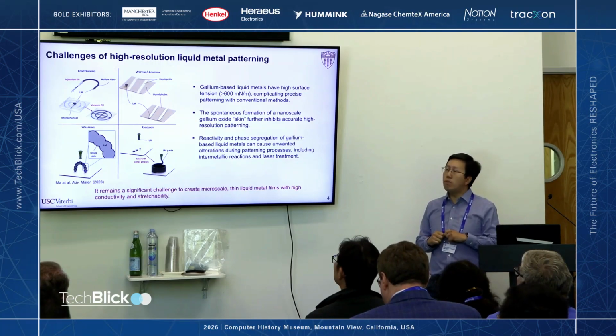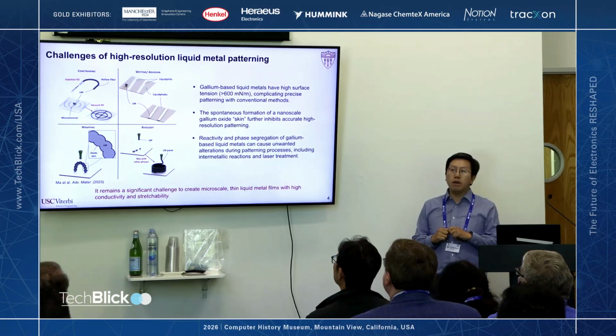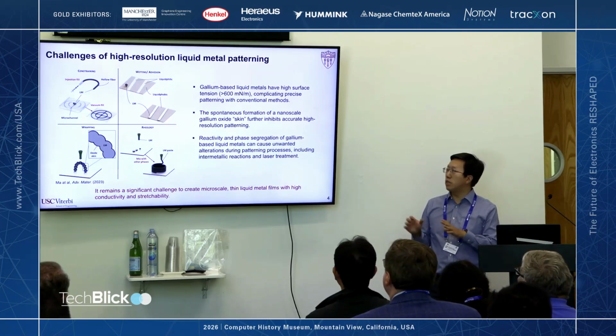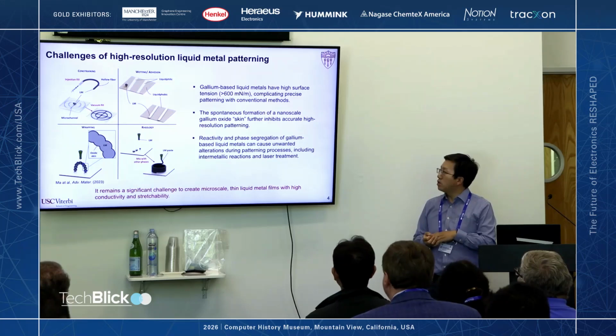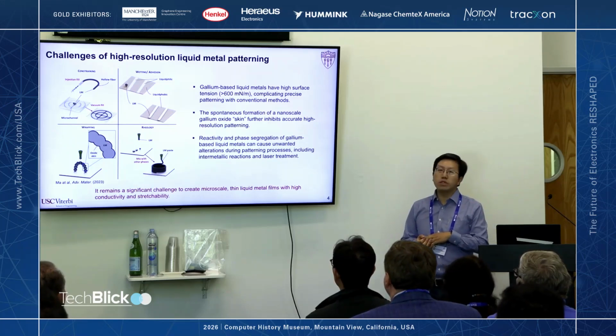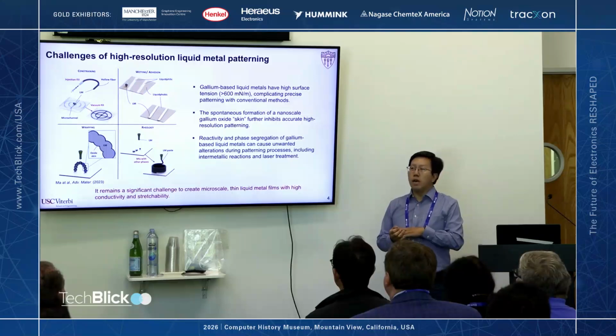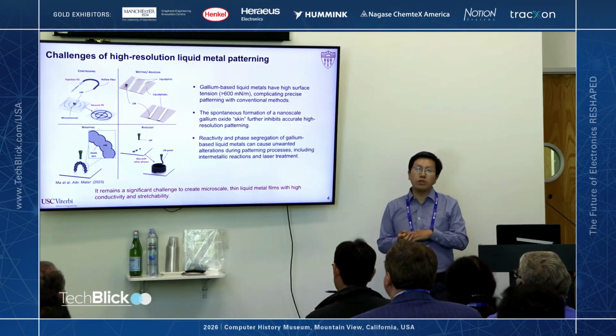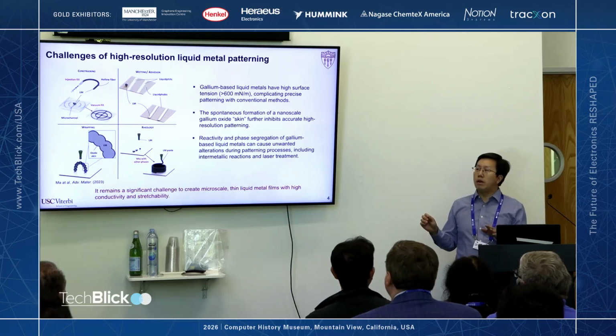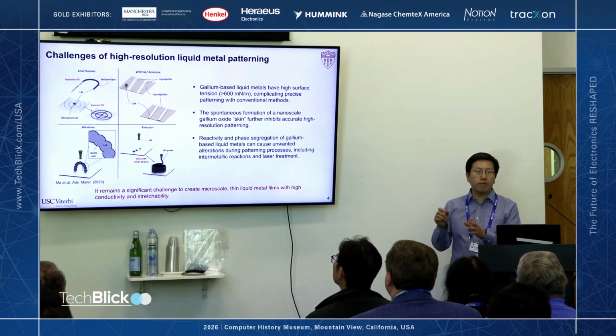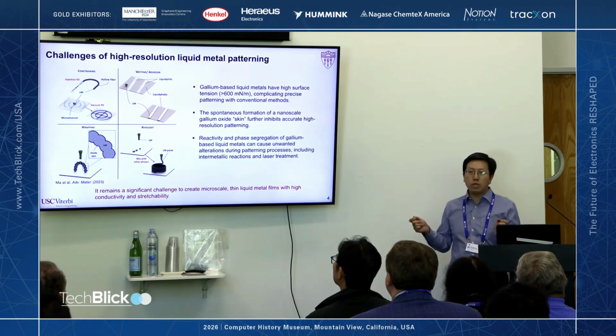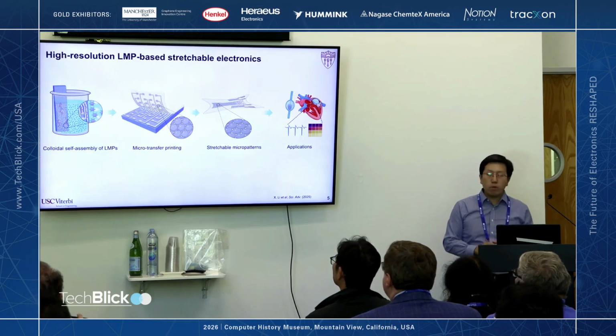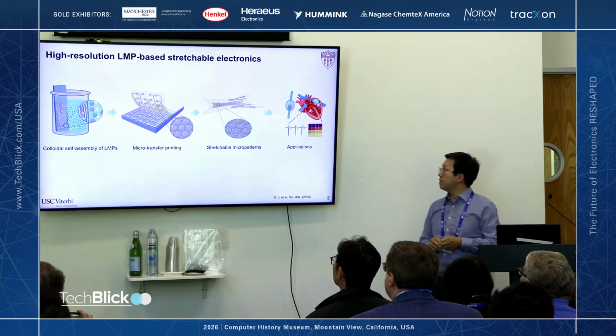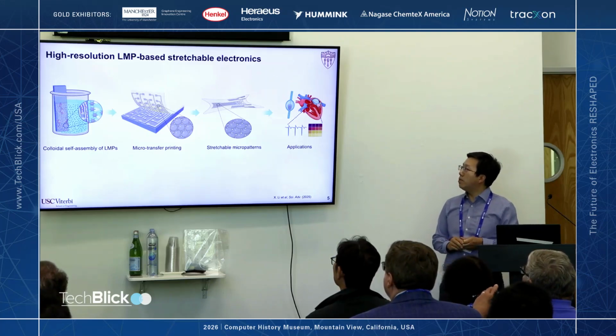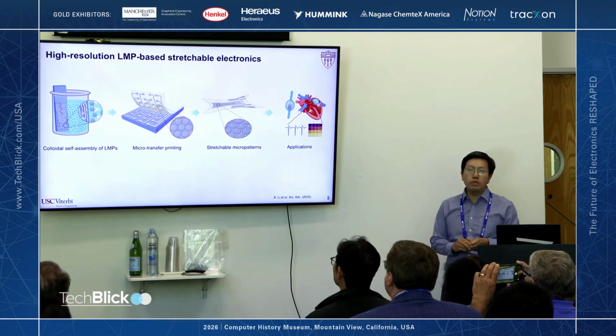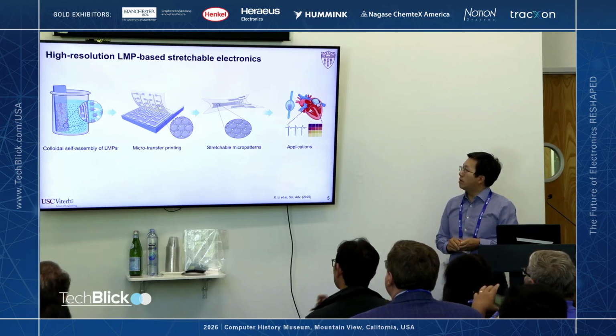Second, it forms a nanoscale thin oxide skin that complicates its interfacial behavior. Because of these reasons, although there are some approaches that can be used to pattern liquid metal, it's very hard to achieve microscale resolution in terms of thickness and line width on a highly stretchable platform. So that's the problem we are trying to solve. In a paper published in Science Advances last year, we think we have found a way to do this. Here's an overview of the process.